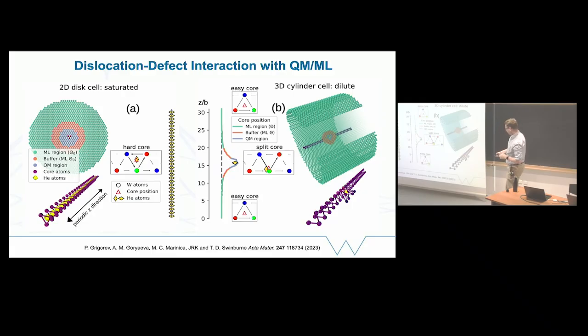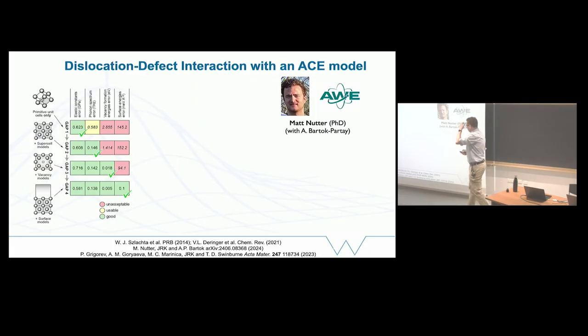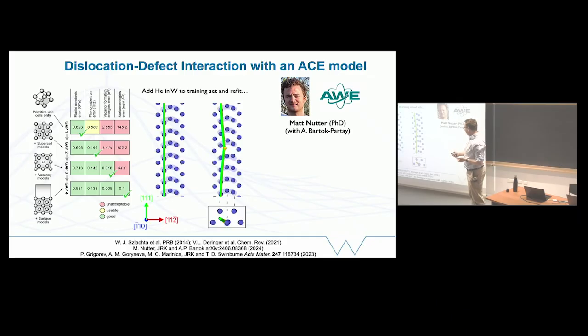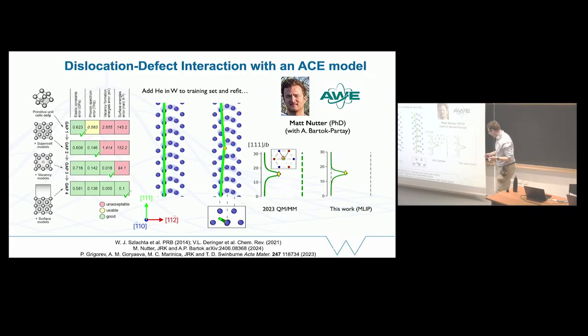And we see a local change. So this is nice. What's even maybe nicer is that a new student, or a student Matt, who's in the final year with me, built a bit further on this and took an existing database for tungsten, for machine learning potential for tungsten, added in some of these configurations of helium interacting with dislocations, and was able to reproduce the same result that we got quite expensively with the QMMM, just with a potential.